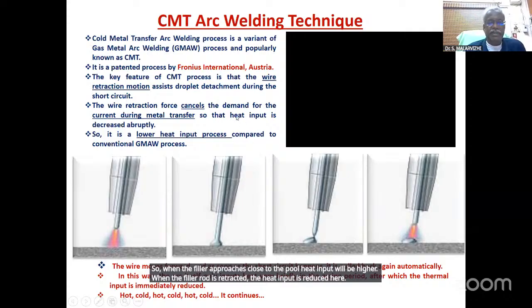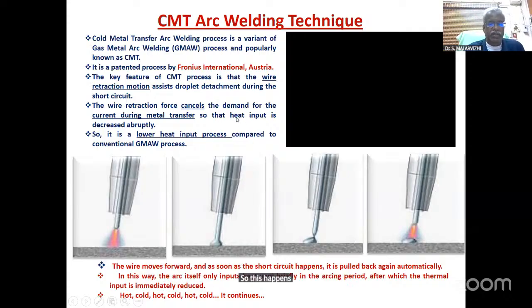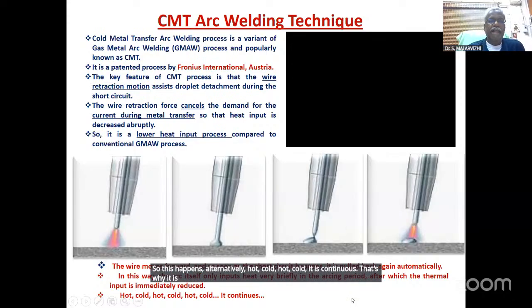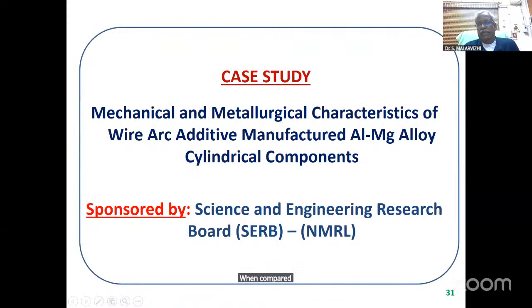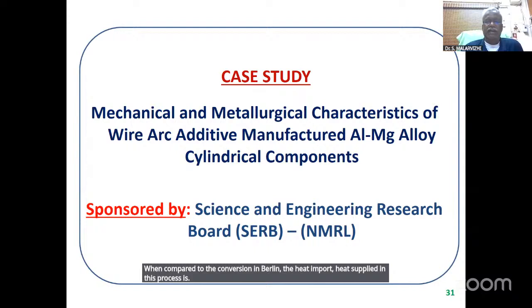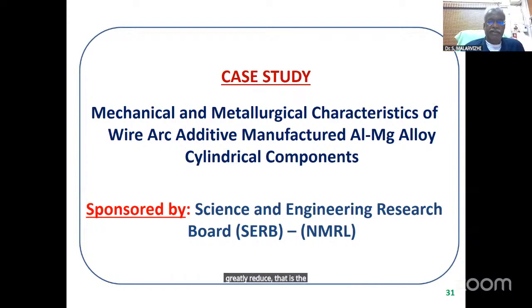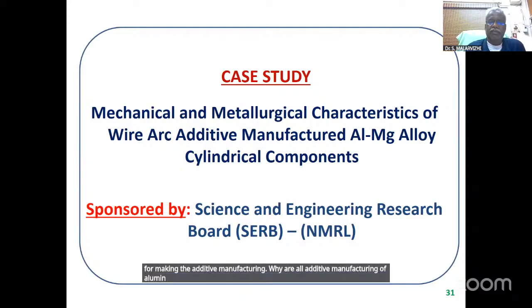So this happens alternately, hot, cold, it is continuous. That's why it is a cold metal transfer. When compared to conventional MIG welding, the heat supplied in this process is greatly reduced. That is one advantage of this process. So we use this process for wire arc additive manufacturing of aluminum cylindrical components.